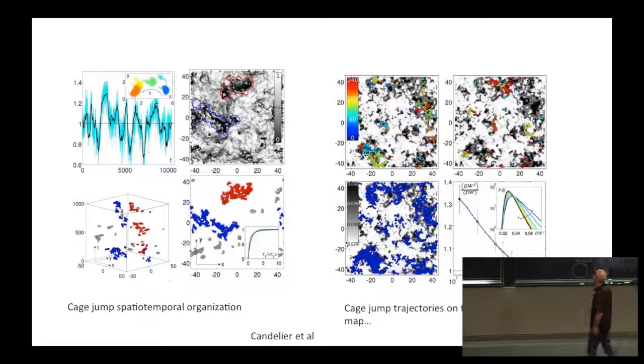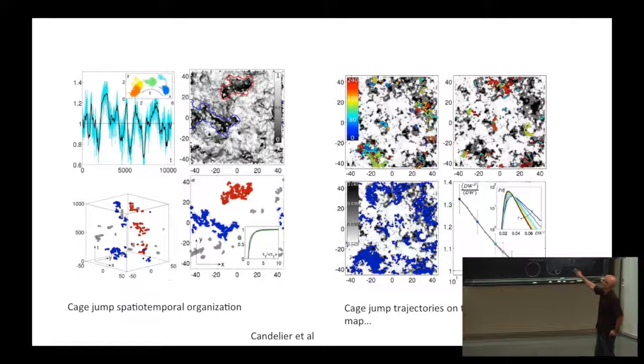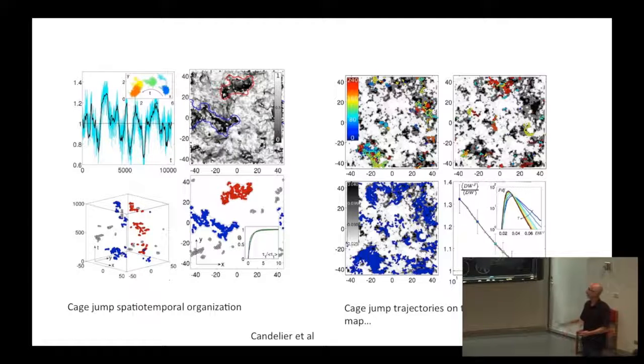And in fact, if you ask how that occurs in terms of the soft modes on a very short time scale, if I calculate the initial configuration and the propensity associated with it, then I get a cluster of cage jumps, let's say in one color here, which begets a cluster of cage jumps nearby, and so on. And over a time scale, let's say a third to a fifth of the natural relaxation time of the entire dynamical overlap, these things sort of live on top of the soft regions of the system.